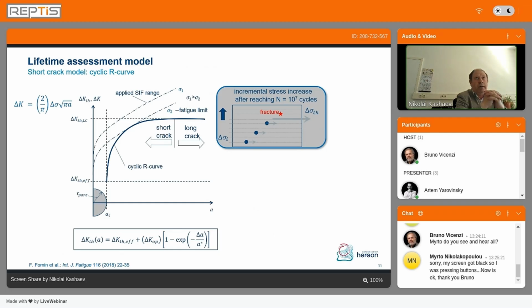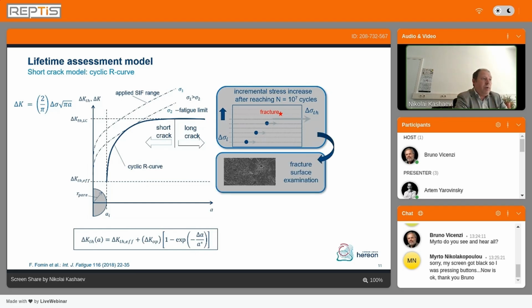For example, we can do fatigue tests up to 10 million cycles, and we can start with a cyclic stress level from the minimum value and step by step increase the level. If the component does not fail at 10 million cycles, we increase the level of cyclic loading and start the fatigue testing again. And if the specimen fails, we assume that something in between is our fatigue strength. Then we can analyze the fracture surface and identify the pore which was exactly responsible for the failure. And for this pore, we know the characteristics, the crack driving force, and considering the tangency condition to our R-curve, we can identify the fitting parameter of our cyclic R-curve. Then we know our cyclic R-curve.